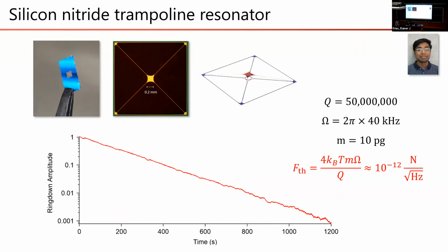So we can make these trampoline resonators with Qs on the order of 50 million, as high as 100 million. They have roughly 40 kilohertz oscillation frequencies. Masses are around 10 picogram. They're large enough to interact nicely with an optical field. Force sensitivities of around a piconewton.